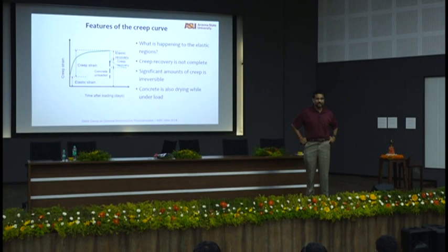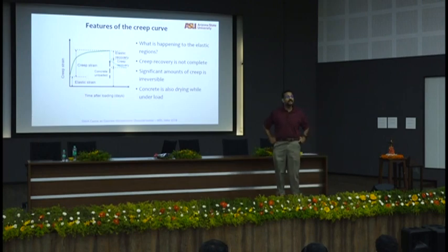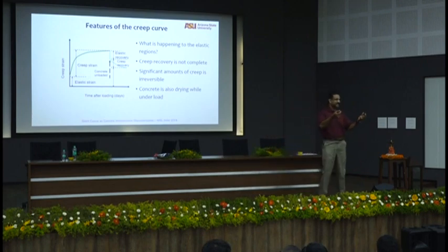Have you changed the elastic modulus of the paste? Right? Your paste is still the same. To overcompensate for the fact that you have put in these rubber particles, you probably might have added more cement and stiffened the paste. Counterproductive, right? You actually had good intentions of making the elastic modulus low, therefore you threw in the rubber particles. So you will see these papers saying influence of soft aggregates on creep of concrete. Nonsense.